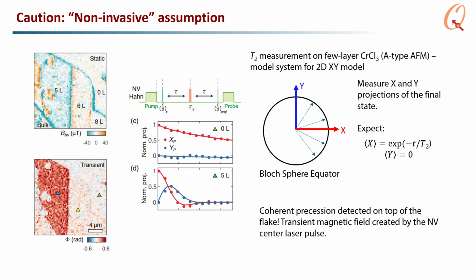But what you don't expect is there to be a preferential Y projection. Actually, on the five layer sample, you see that Y goes up, whereas if it was pure decoherence, Y should stay at 0. So this is not pure decoherence. We're getting a coherent precession on top of the flake.